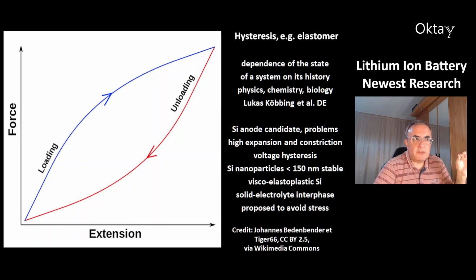There's another work of Lukas Köbbing and colleagues from Germany. They made a research on the element silicon, which is a very good anode candidate. However, there are problems with high expansion and constriction, and this material has a voltage hysteresis. But there's a trick, and the trick is using silicon nanoparticles that are not bigger than 150 nanometers. These are stable. And these scientists propose using a viscoelastoplastic silicon to solve this problem with a solid electrolyte interface to avoid the stress during charging and discharging.